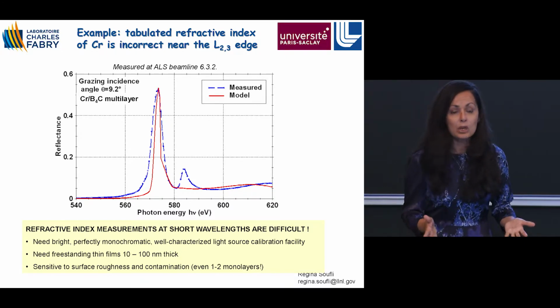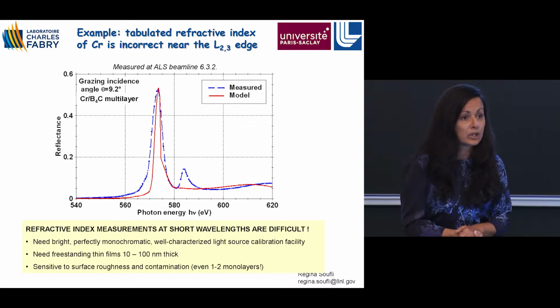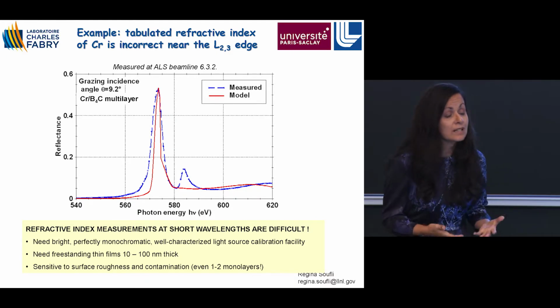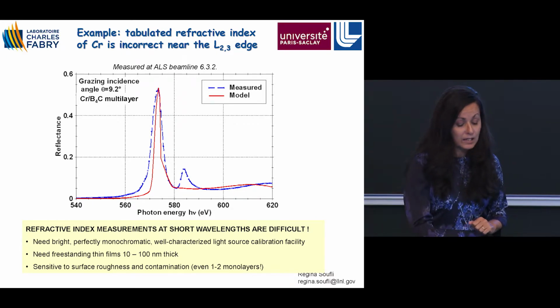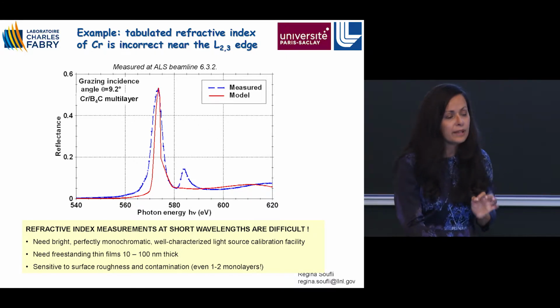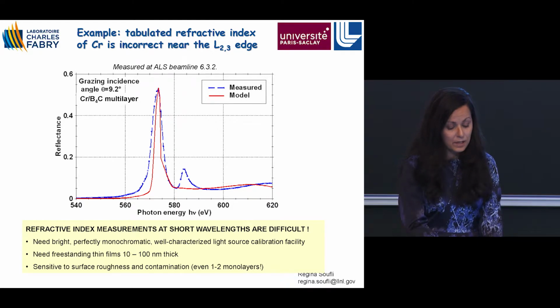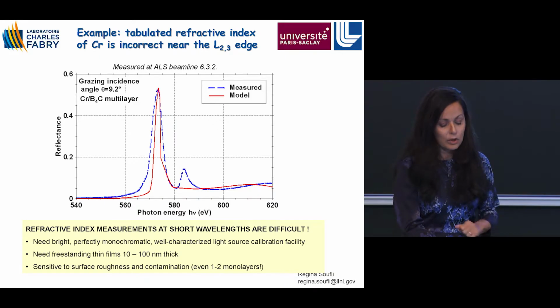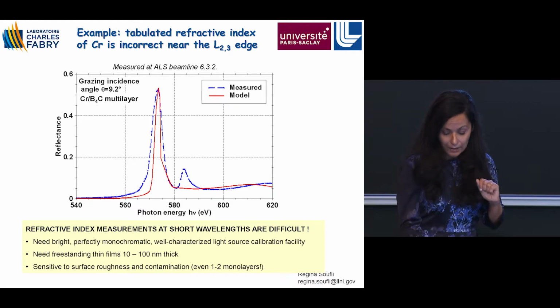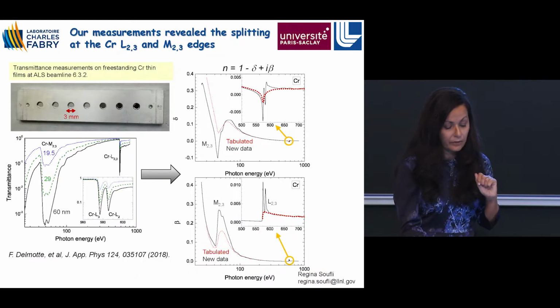And so it's very surprising because chromium is a very important material for science and technology. At the same time, it's not surprising because these measurements are extremely difficult to make. Just a few of the challenges I'm highlighting here. You need a perfectly bright, perfectly monochromatic, well-characterized light source and calibration facility. You need extremely thin freestanding films, about 10 to 100 nanometers thick. And if you do reflectivity measurements for your refractive index, you're also very sensitive to surface roughness and contamination at the monolayer level.